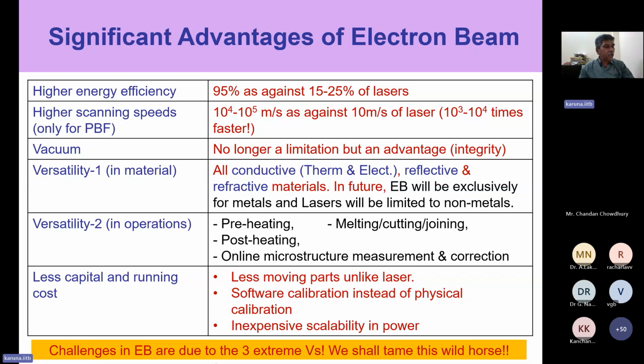In this slide, I have listed the significant advantages of electron beam. I already told you energy efficiency can be as high as 95%, because electric energy becomes heat energy, whereas laser is hardly 15 to 25%. Then the scanning speeds: we are able to get as high as 10,000 meter per second, compared to a laser, which is 10 to 100 meter per second. So this gives it a lot of possibilities.